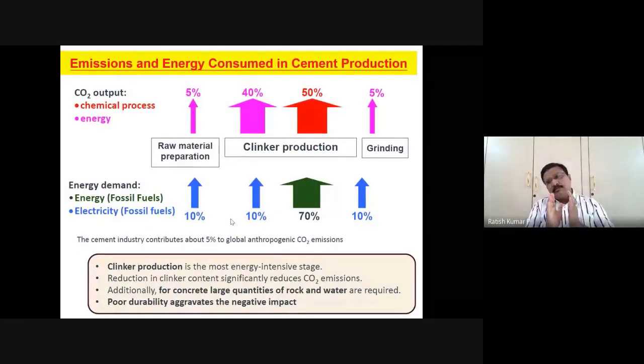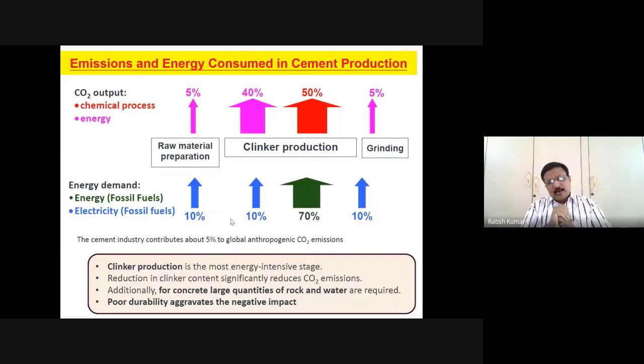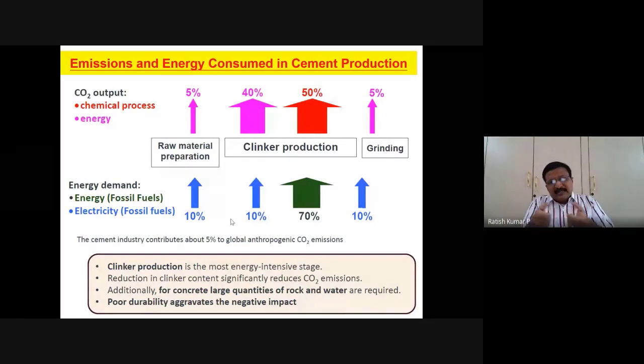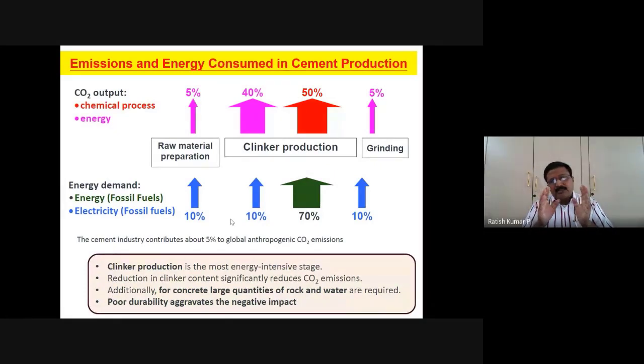Now, let me talk a little bit about cement production. Some of you might have studied it; some students and research scholars are here. I want to talk about this aspect very briefly. When you talk about cradle to cradle or cradle to grave, the production of cement passes through several stages. We talk about argillaceous and calcareous materials, pre-calcination, and the grinding and heating of these materials in the rotary kiln, which passes through several temperatures, for example 850 degrees centigrade for belite formation and 1300 to 1350 degrees centigrade for alite formation. In raw material preparation, a good amount of energy is expended, including the quarrying of the limestone, which is a very important aspect.